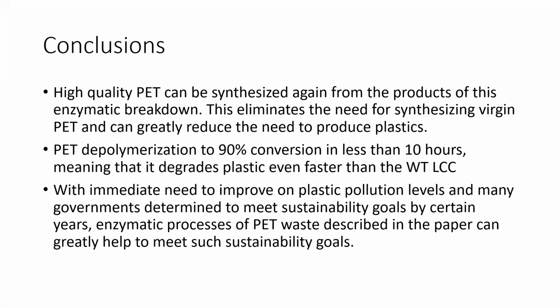This study demonstrates that high-quality PET can be synthesized again from the products of this enzymatic breakdown. This eliminates the need for synthesizing virgin PET and can greatly reduce the need to produce plastics. So the optimized enzyme in this case achieved a 90% depolymerization.